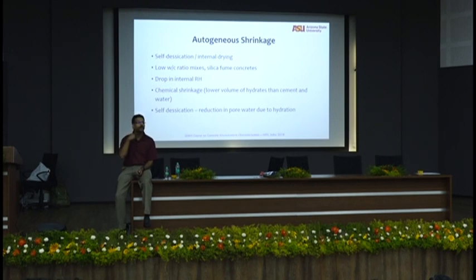Autogenous shrinkage, yeah. Chemical shrinkage, every concrete, every reaction, every damn thing that you react one with the other has a chemical shrinkage. Really, does it influence? Depends. So be careful when you parse these terms, so that you don't use the terms for the sake of using if you don't need it. For example, if you're doing volume changes in concrete, if you're doing everything from the perspective of cracking in a concrete bridge deck or a concrete pavement, forget autogenous shrinkage, forget chemical shrinkage. You'll be better off with drying shrinkage by itself.